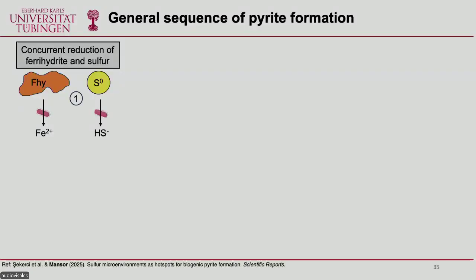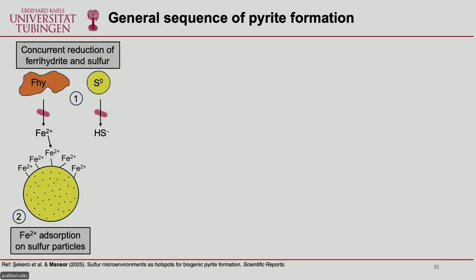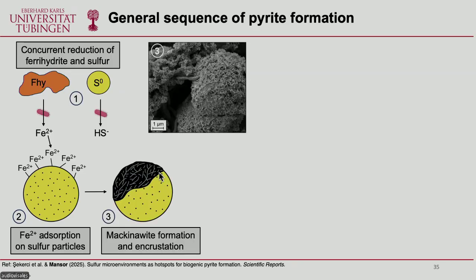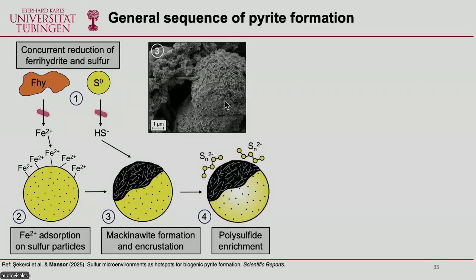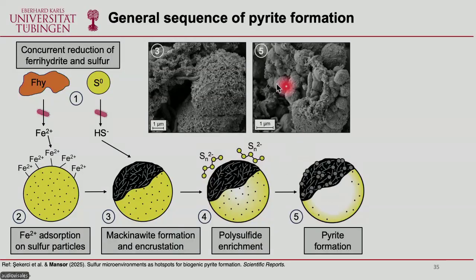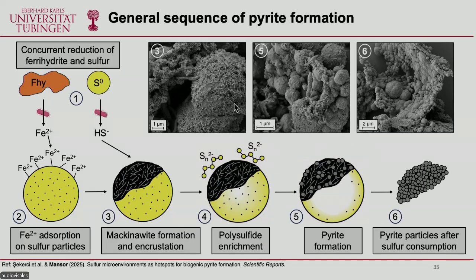And so we can come up with a general sequence of pyrite formation for all conditions. We have concurrent reduction of the iron minerals and sulfur by Geobacter. This then allows for iron(II) to be adsorbed on sulfur particles. And then we can form mackinawite specifically on the sulfur particles. Over time, this creates a zone where there's a lot of reactions happening, and then we start to see pyrite also starting to encrust the sulfur particles. Over time, the sulfur particles disappear, and sometimes you see these structures where there's a shell of pyrite remaining. And so we can form pyrite clusters, but not framboids.